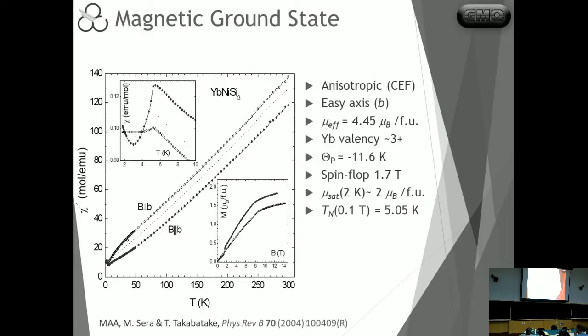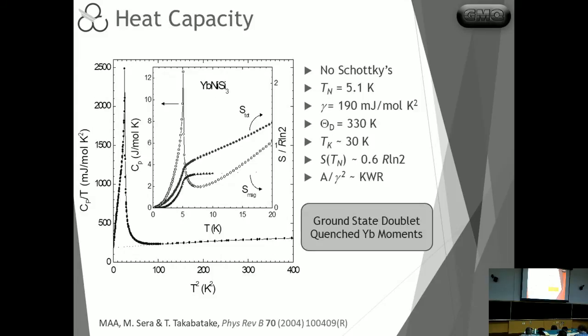The magnetization is anisotropic. The easy axis here was found along the b-axis, and when we measure the effective moments, it's very close to the expected ytterbium valency, which means it's very close to +3. In this case, we do see a spin flop here, right at around 1.7 Tesla. But although the valency is very close to +3, you can see that the saturation moment here at high fields is still quite below what we expect from the ytterbium moments. So it seems that's characteristic of a quenched system that is hybridizing with conduction electrons.